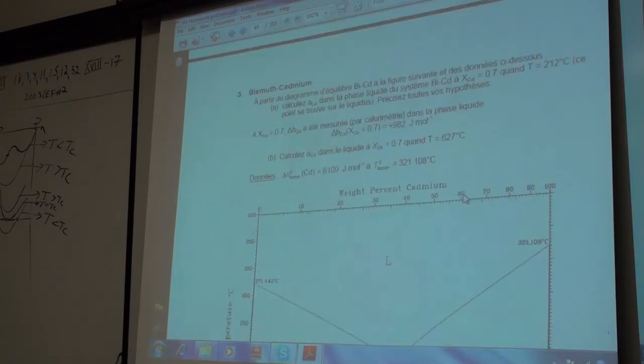So 0.7 is here, and 212 degrees is on the liquidus temperature. So calculate the activity of cadmium on the liquidus. Secondly, calculate the activity of cadmium at the same composition, but at a higher temperature of 627 degrees Celsius. So we're going to calculate first on the liquidus at 70%, and then at the same composition we're going to calculate it at a higher temperature.